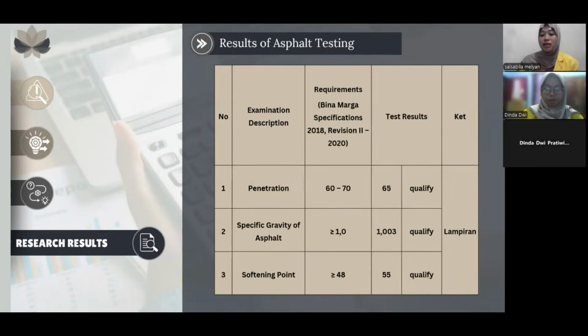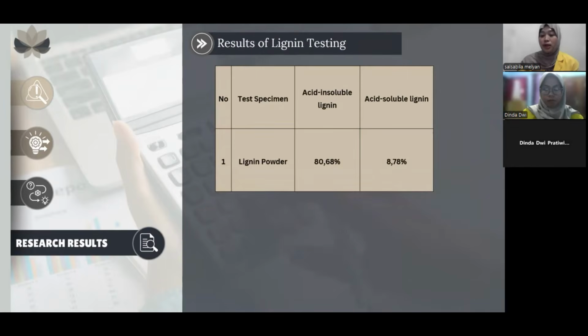The Pen 60/70 asphalt test shows good results. Penetration is 65, specific gravity is 1.003, and softening point is 55 degrees Celsius. All parameters meet the standard. The lignin test shows good quality. Acid insoluble lignin is 80.68% and acid soluble lignin is 8.78%. This lignin is good for asphalt mix.